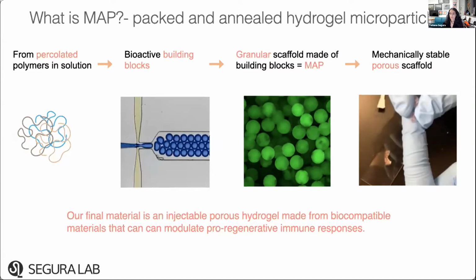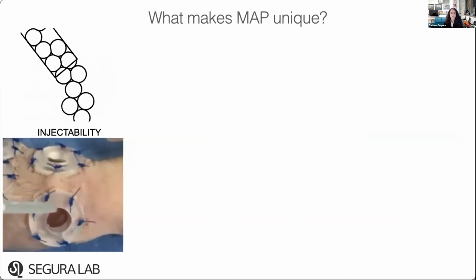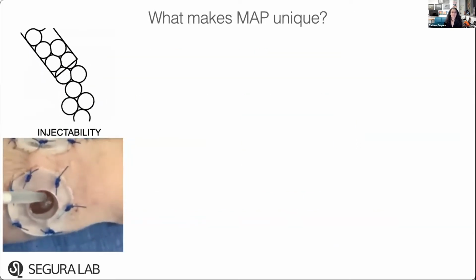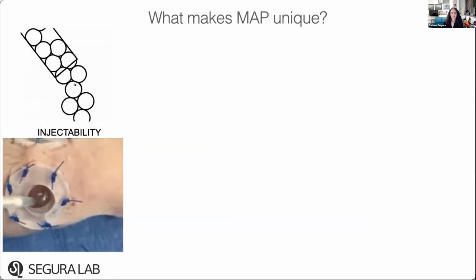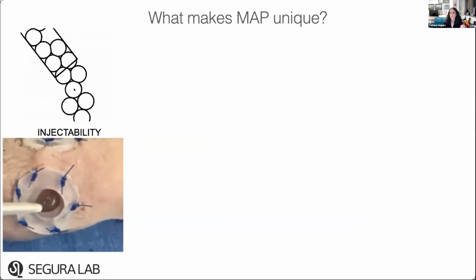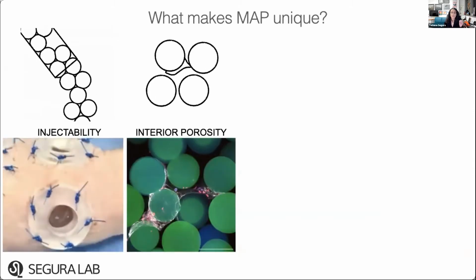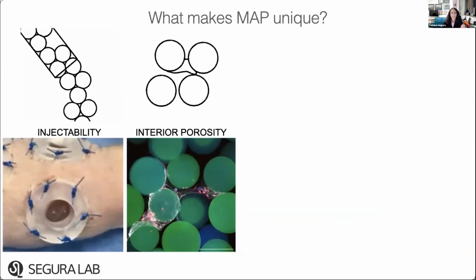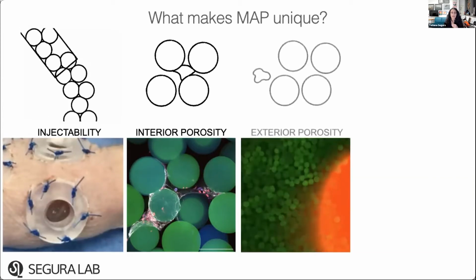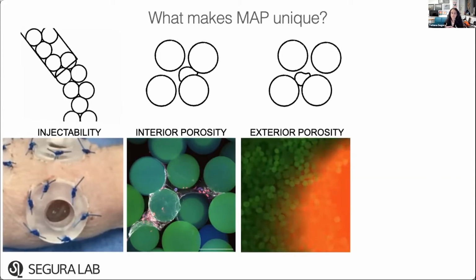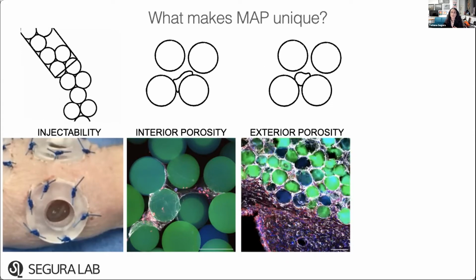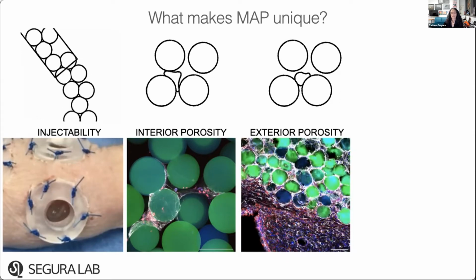You can see examples here of our particles. And here is an example of a stable gel. If you take these particles and interlink them with each other, you actually form a stable scaffold. What is so unique about this material is that it's injectable, because the particles are smaller than the 30 gauge needle. They have interior porosity, so cells can infiltrate through the material. They have exterior porosity so that the nutrients can flow in. And if you plant them, for example, in the brain, you see that there's rapid cellular infiltration into the material.